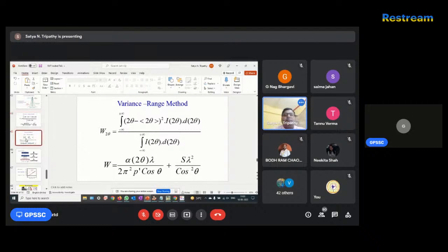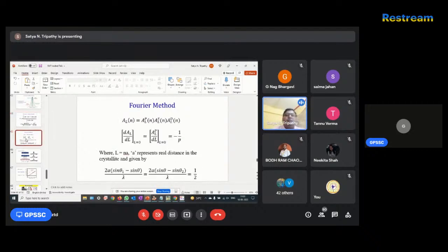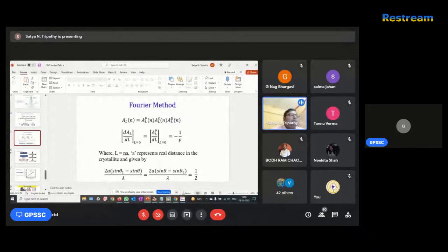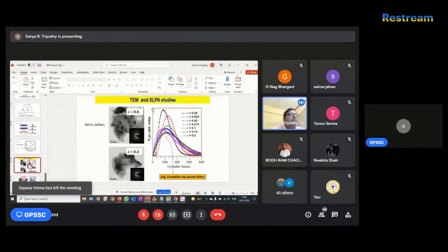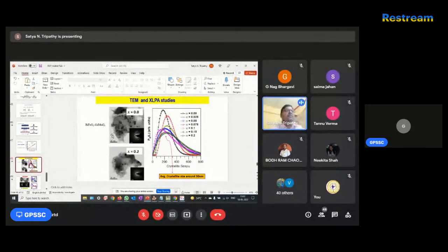Next is the Fourier method. In the Fourier method, the total broadening will be due to size, strain, and the lattice part. If you do this analysis, the Fourier deconvolution, you are going to get the distribution. Suppose I have the TEM result here, and this is the Fourier result. You will have a distribution of the crystallite size. I am showing this for the GdVO4 system, published in, I think, Materials Research Express. For all the samples you can see the distribution, the average crystallite size in nanometers, and the same data you can correlate with the TEM data. This X-ray line profile analysis gives results very close to the observed data.